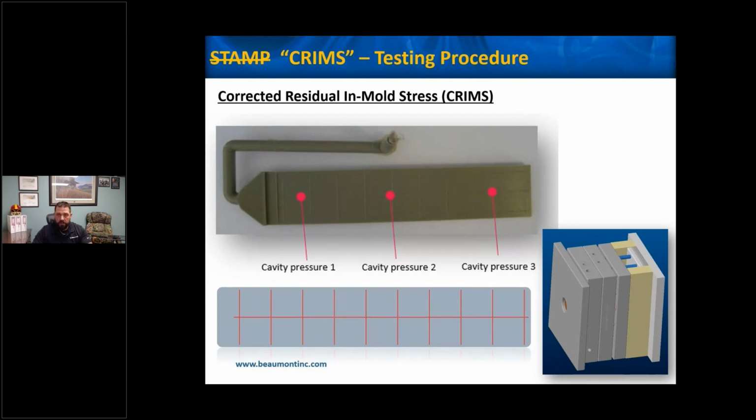Step 4, post-molding. So after the samples are molded, the samples are annealed for a nominal 1 week duration, and this just allows stress relaxation over time. So we're not measuring samples right at the end of the molding cycle. We want to make sure that if it is a semi-crystalline material, we give adequate time to go through crystallinity changes over time. So in a lab environment, those samples are annealed for a duration of 1 week.